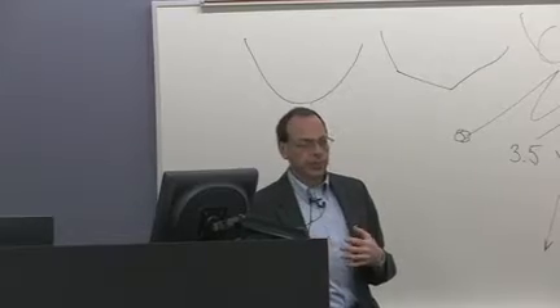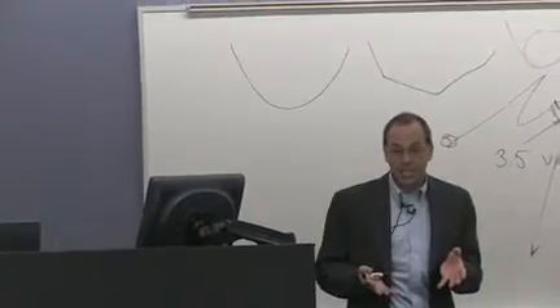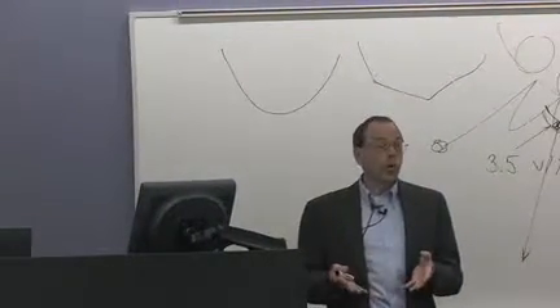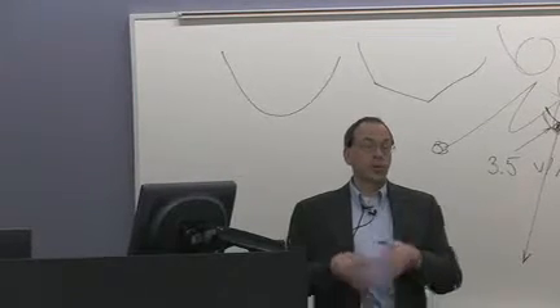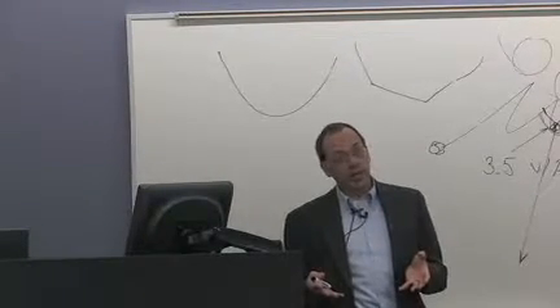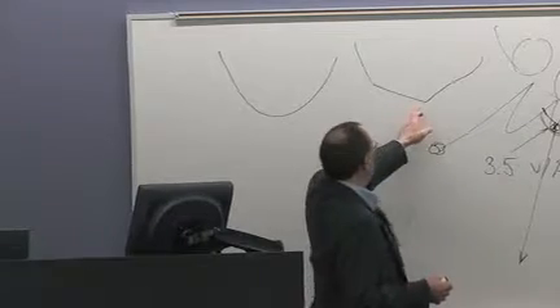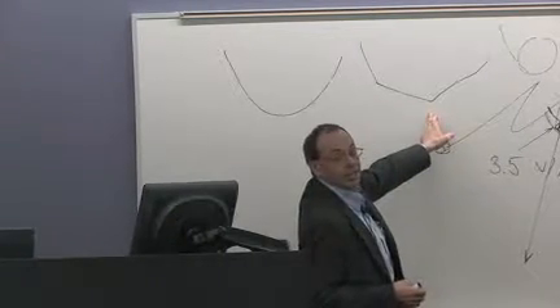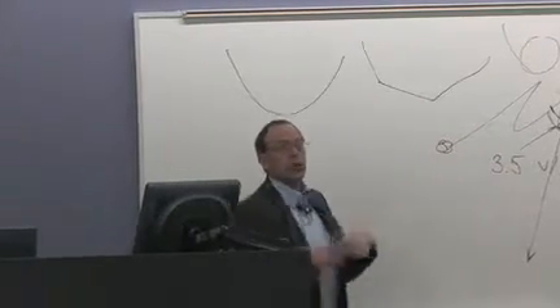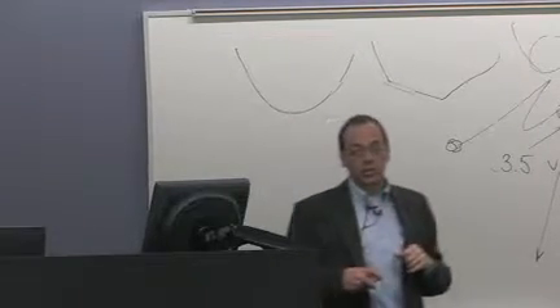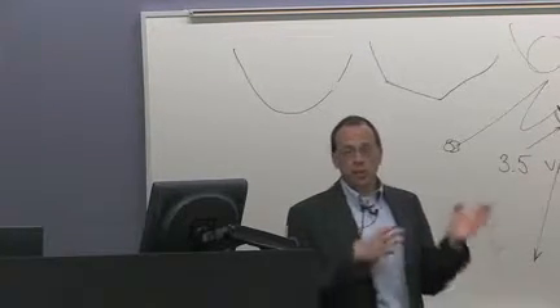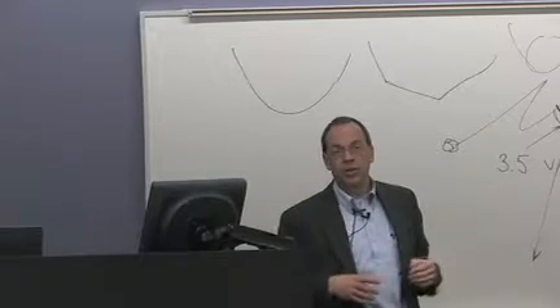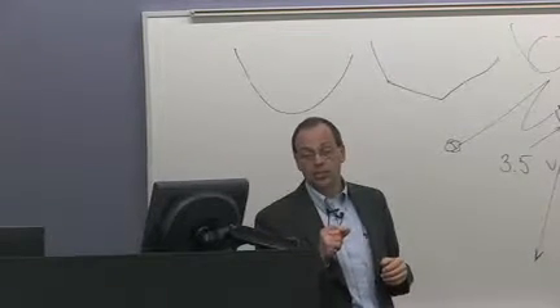And all of that surface science that tells people how to induce faceting, we do that automatically in the instrument. So it's a UHV system. We don't actually have to open it up in order to go from here to here and back. Thank goodness. So you can do that, and it takes maybe a half hour to reshape the tip, and you can operate for 3 to 10 days with that single atom at the tip.